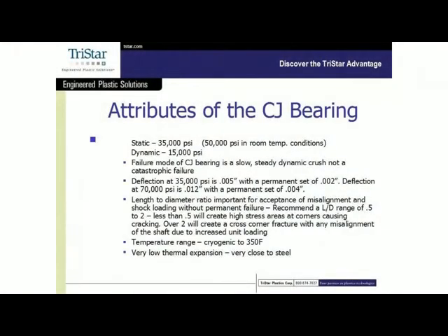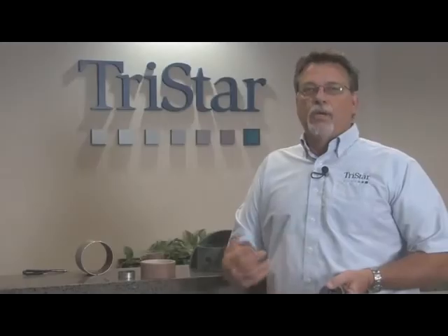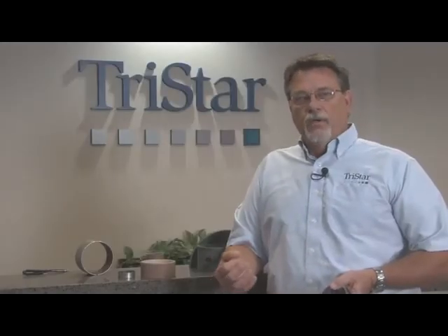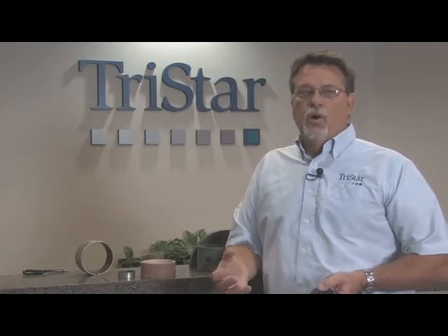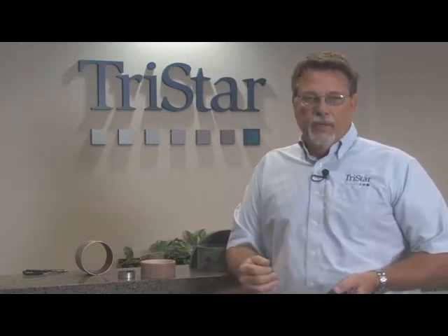Deflection at 35,000 psi is about 5 thousandths, which means that the actual wall deflection is very limited, and the permanent deflection, or the permanent set, is only about 2 thousandths. At 70,000 psi, we'll see a 12 thousandths deflection, but the permanent is only 4 thousandths. So even at the extreme loading conditions, the permanent change in the wall is very, very minimal.